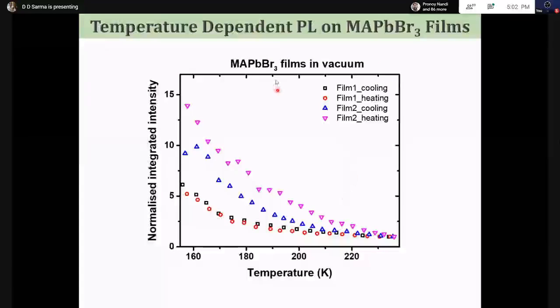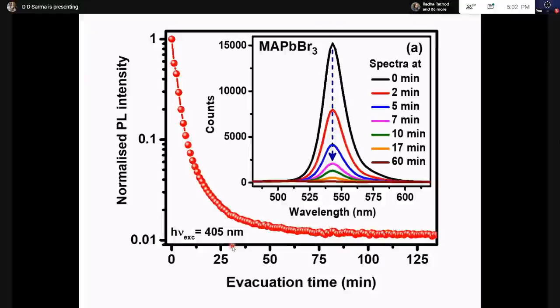Except the problem is, you take the same material and make measurements on different days, different years, different students, different proclivities, and you get different kinds of dependency with the temperature. Which means if I fit it and try to extract the binding energy from here, all of them will give me different binding energies. What is going on? Why is such a thing happening? We realized, and this was seen by other people also, there's a fundamental problem. In order to do the experiment of photoluminescence with changing temperature, you want to put your sample on some cold stage whose temperature can be changed.